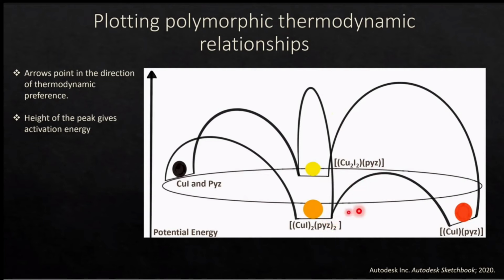But we see that the orange and the red are able to interconvert quite easily, and so we know the activation energy must be quite small between those two. So this allowed us to just get a better feel for the relationships. But one thing you do not see is copper iodide and pyrazine spontaneously forming the red compound without first going through the orange intermediate.